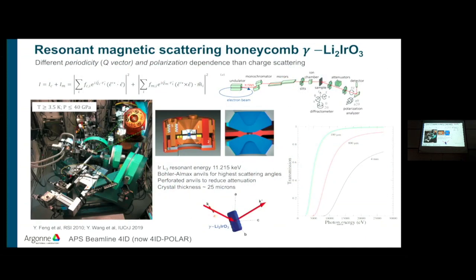So we do these experiments. We have to square the scattering amplitude. We have the charge term and the magnetic term. And we want to do these experiments at high pressure, because what we want to do is see if we can tune these angles and these distances to bring it into a more regular honeycomb lattice.